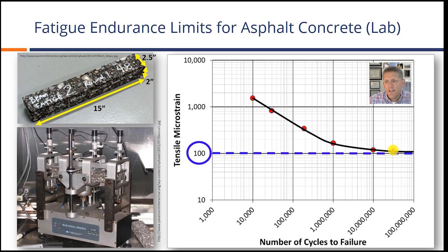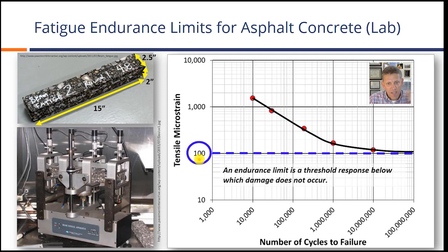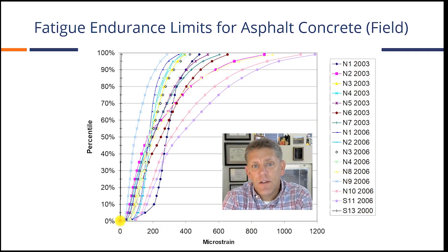And we call that the endurance limit, and that is defined as the threshold response below which damage does not occur. So if we're designing the pavement and we know it can handle up to 100 microstrain before it would crack, we design it just thick enough so that we're below that 100 microstrain limit. If we're below the endurance limit, we do not get bottom-up fatigue cracking in that pavement. So that's how we come up with it in a laboratory.